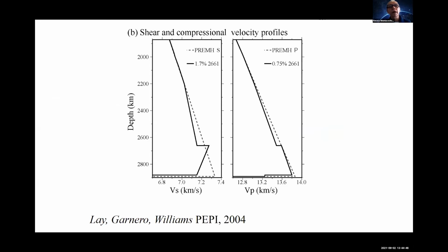But what was really remarkable was the prediction of velocity discontinuity across this phase transition. At low temperatures, the phase transition occurs at lower pressures, and that's where there's a better chance to see this phase transition in the mantle. And this is the discontinuity in shear and compressional velocities. Relatively, the discontinuity in shear velocity is larger than compressional velocities, pointing to an anticorrelation between the change in bulk modulus and change in shear modulus.